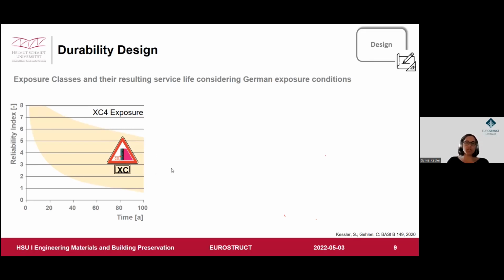But if we check the normal limit state, which is normally a beta value of 0.3, we can say that we can easily ensure a service life of about 50 years, and there is only a very low probability of corrosion if you would like to ensure a service life of 100 years. So if you apply the rules appropriately, you will probably not have any issues with carbonation-induced corrosion. As the next step,